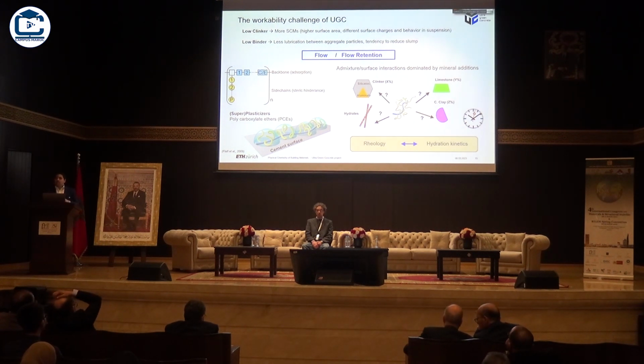On top of that, there are a lot of admixtures, particularly from the family of PCE, that are known to hinder the hydration of alite or C3S. So there is a counterplay as well, as we were talking about in reducing the clinker factor, between keeping rheology, keeping flowability, open time and initial flow, versus hydration kinetics, and we need both. And there is certainly an optimum between the two, and what we need to achieve is basically to develop a new generation of admixtures for this cement that enable us to get flowability without sacrificing early age performance.